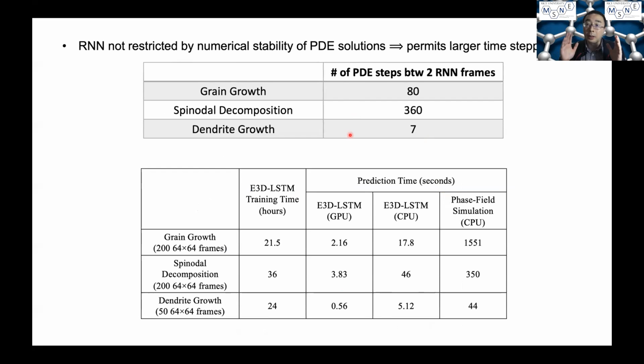So the microstructure evolution governing equations are often nonlinear high-order PDEs, for example, in phase field models. This often places a quite severe limitation on the time step size you can use in a PDE solver. But when you use machine learning to make predictions, we're no longer restricted by these limitations. So we're able to use large time step size to make predictions of the next frame, how they evolve.